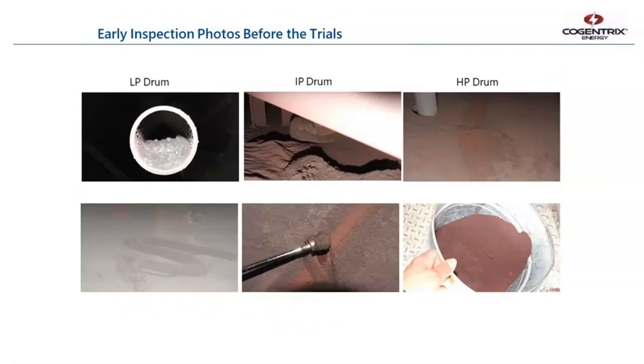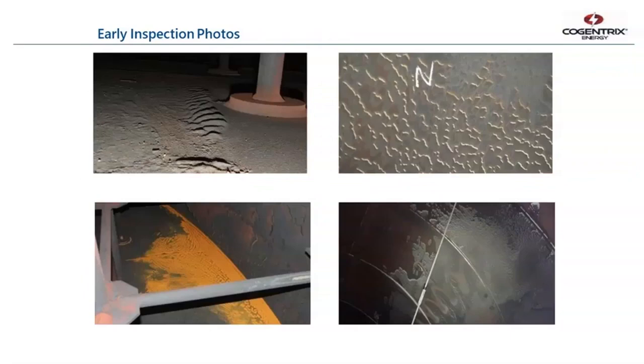So here are some photos. This is what the plant looked like, internal inspections before we started using amine based filming products. This was all on AVT-O with a pH of 10.1. Piles of iron everywhere, quarter inch thick in the drums in some places. The photo on the upper left is the monkey bars area. You can just see piles of iron on the ground. The one on the right is in the turbine exhaust area. Right after it comes out of the steam turbine on the wall, you can see two-phase FAC.